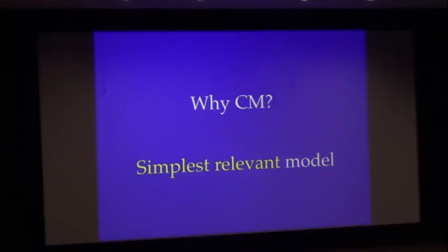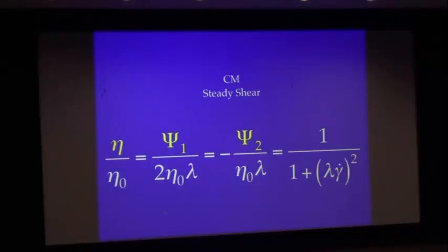So now this is a Maxwell model, but no ordinary derivative here. It's a co-rotational derivative. When you do that, you see the viscosity now will depend on the shear rate. See, when the shear rate gets big here, the viscosity goes down. We call that shear thinning. What's more, you will get a first normal stress difference. I think it's amazing that in 1911, Jaumann could see these things would exist, but we weren't able to measure them until decades later. But the first normal stress difference will also descend with the shear rate, and so will the second normal stress difference, and this will even have the right sign. It'll be the negative of the first normal stress coefficient. We didn't actually know that to be correct until the 1960s.